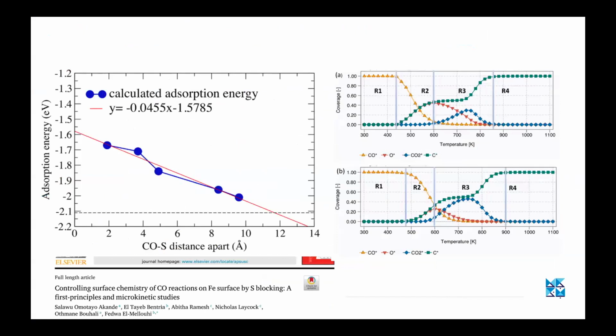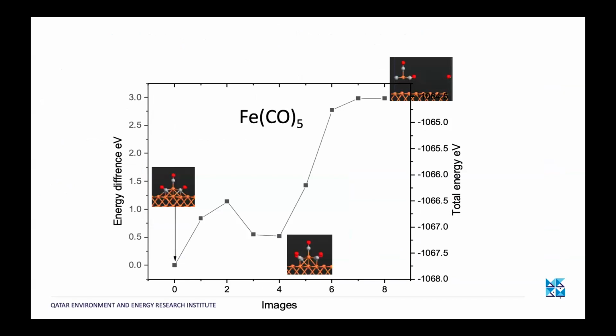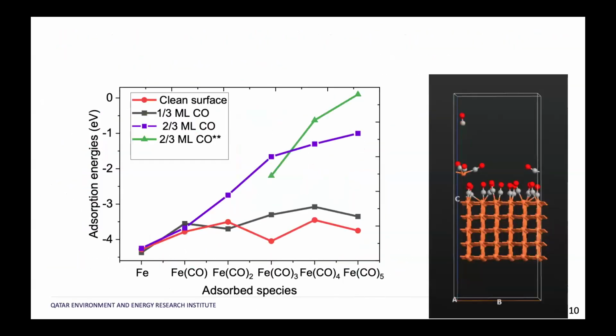En fait, ce qu'on a fait, c'est qu'on a publié ce travail, puis il fallait justifier ça justement. Donc on a regardé la distribution de charge sur la surface. Et ce qu'on a remarqué, c'est que le soufre, une fois absorbé sur la surface, n'est pas un donneur de charge. Il deplete the charge. Donc il prend la charge de la surface, ce qui induit que l'énergie d'absorption du CO diminue dans ce cas-là, parce qu'il y a moins de charge sur la surface. C'est ce qui explique ça. On l'a fait avec une analyse très similaire à ici, charge density analysis.